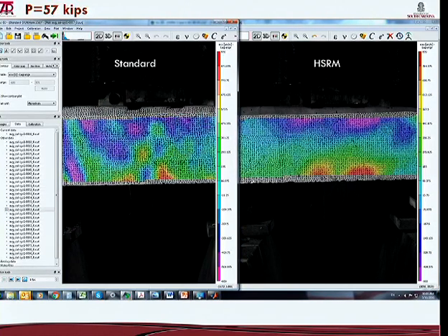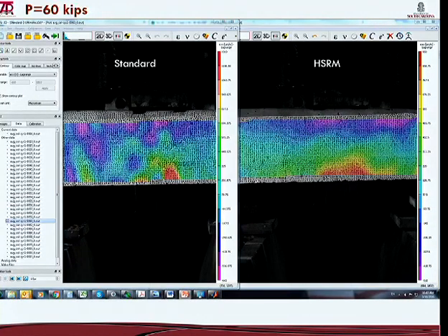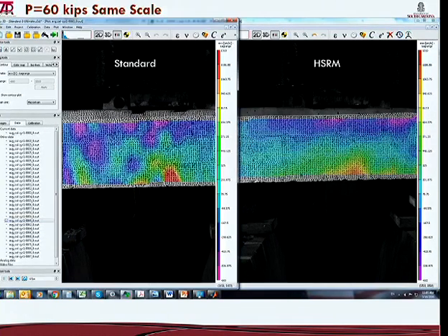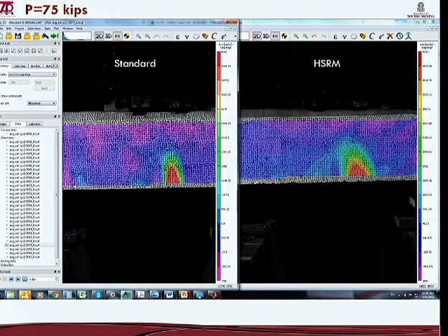Now 57 kips, clearly stress concentration. Then we see two areas of high stress, and now the values here are still at 870, and no crack had been monitored. It's just the way the load is being redistributed. 60 kips, same story. Now the crack starts propagating, the load gets distributed, and this time we look at the strains here. We jumped up to 4,000, 4,000. Here's a crack. Here's our crack.